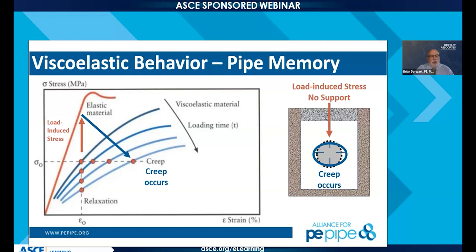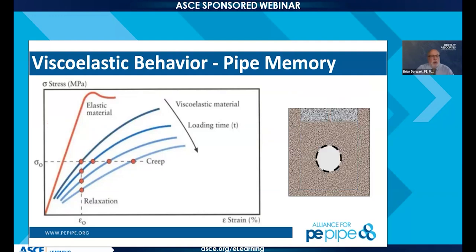So if you have a constant load on it over time, it's going to continue to move until it can balance it. And that's what these different curves show: as you increase the amount of time, the creep has more and more effect. In other words, it stretches more. That doesn't necessarily mean the strength has changed, or that the modulus under the elastic portion has changed. However, the modulus for your design, you have to take into account the creep factor, and that's what this chart shows. You treat it differently than you would an elastic material. The whole idea is understand the material, design for the properties of the material, and you'll be fine.